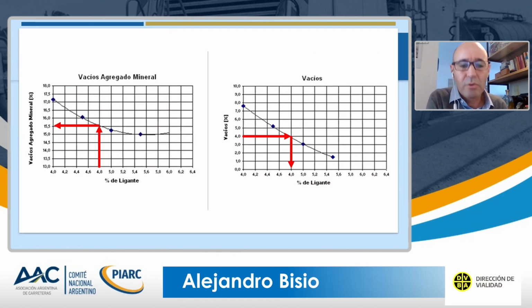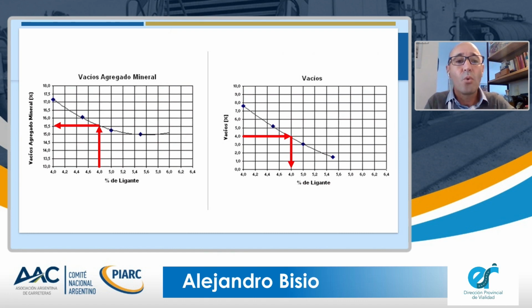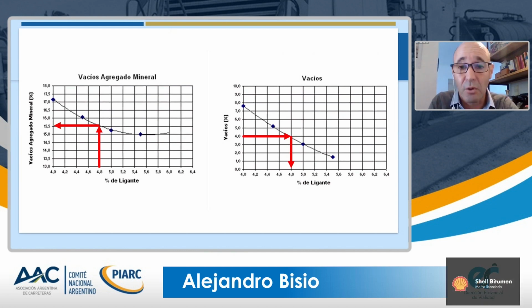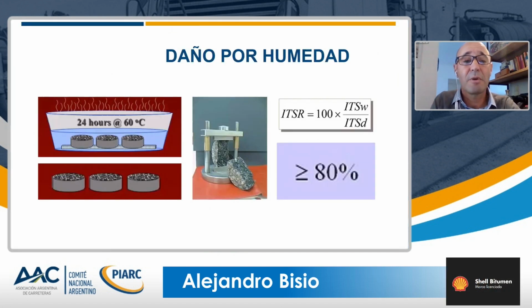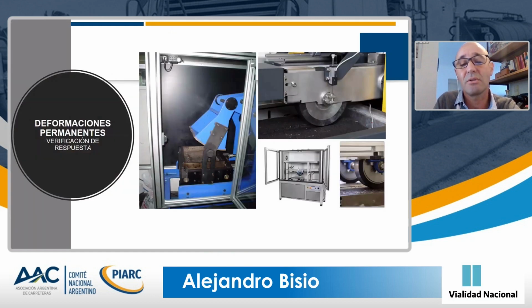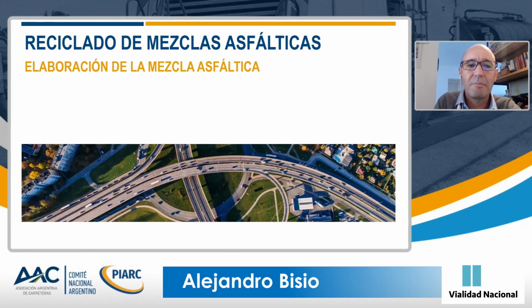Once we already had the granular structure coming from the aggregate blend and the asphalt binder, we fixed as design criterion the asphalt content with 4% empty voids or holes. So then we tested mechanically this material against wetness damage and permanent deformation through the wheel tracking test.